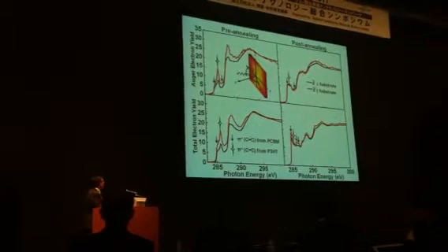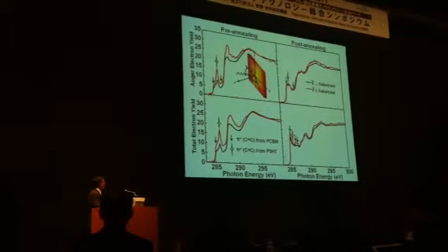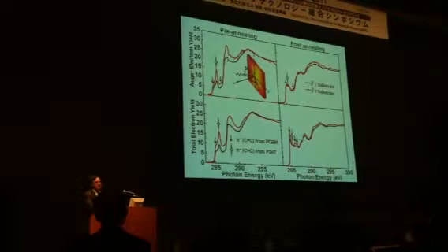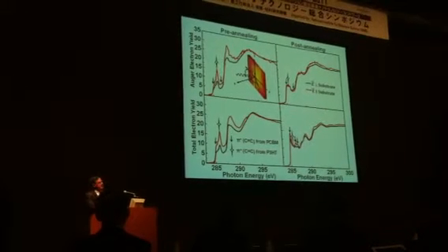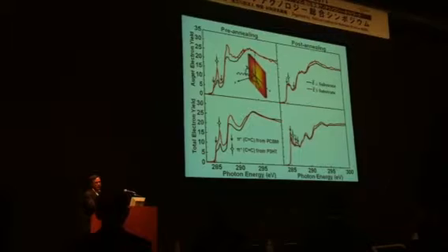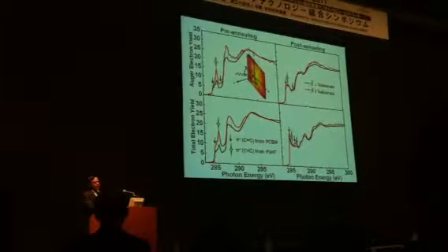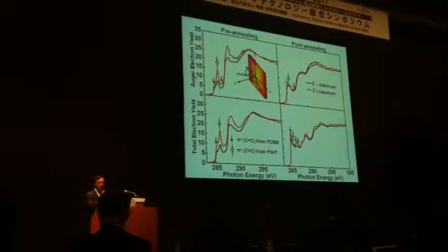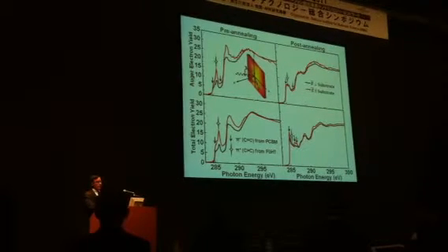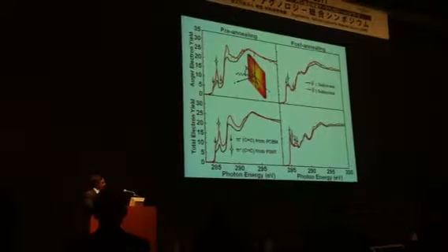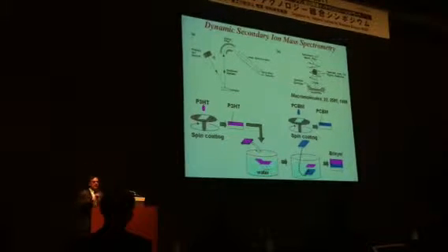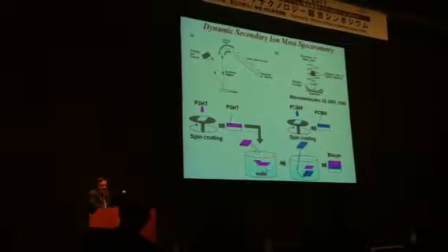And in fact, what you find with the post-annealing case is that you have the segregation of the PCBM at the surface, which is telling you that you're getting this segregation of one component to an interface, and that's very important in terms of being able to understand the structure of the material right at the interface where all the action effectively is occurring in terms of the transport of electrons or holes from an organic material to an inorganic.